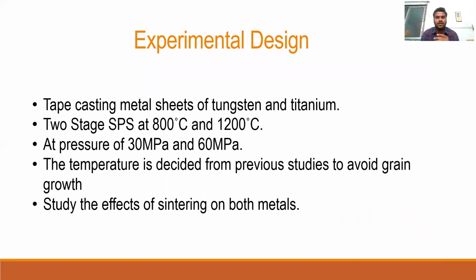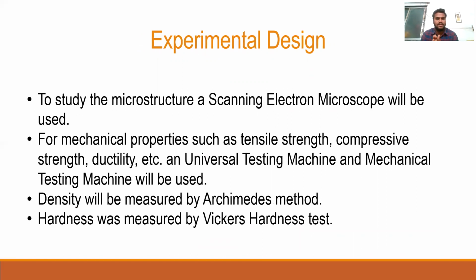So I designed the experiment in such a way that I will first cast the metal sheet of tungsten and titanium by tape casting. Then two-stage sintering will be carried out at 800 degrees Celsius and 1200 degrees Celsius under pressure of 30 MPa and 60 MPa respectively. The temperature is decided from the previous studies to avoid the grain growth, as I said earlier. Then we study the effects of sintering on both the metals.